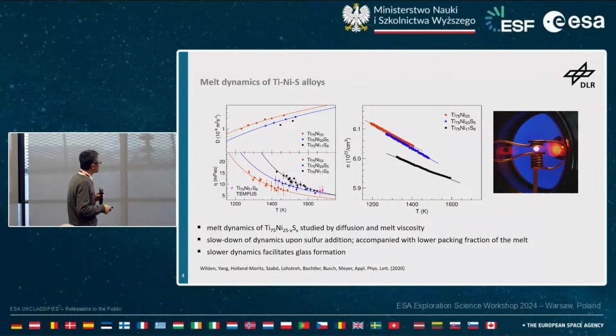And this can be somehow understood as to why the glass forming ability gets better, because if you have slower transport and you quench it, it's more difficult to crystallize. But we also studied the solidification behavior, and if you look at the details, there's actually a bit more than just slower dynamics in this case.